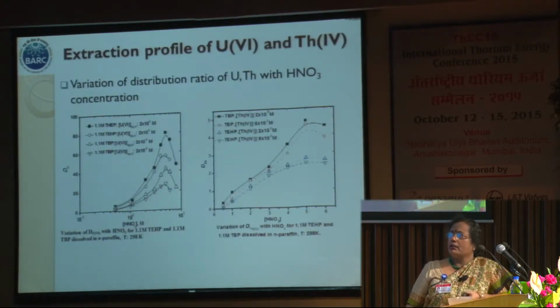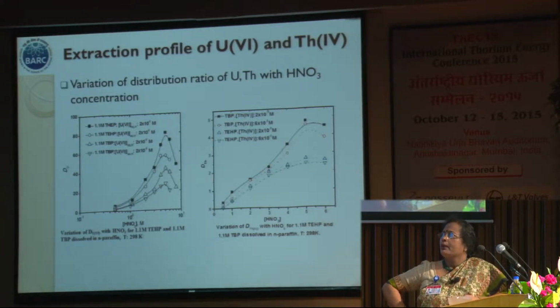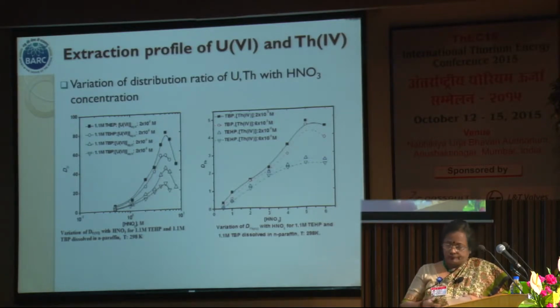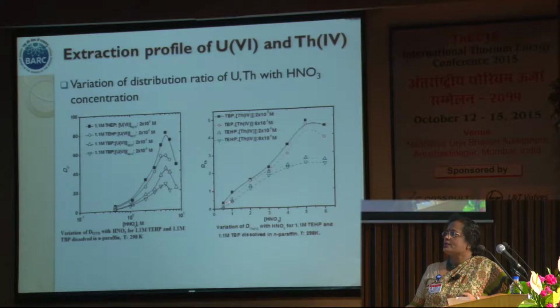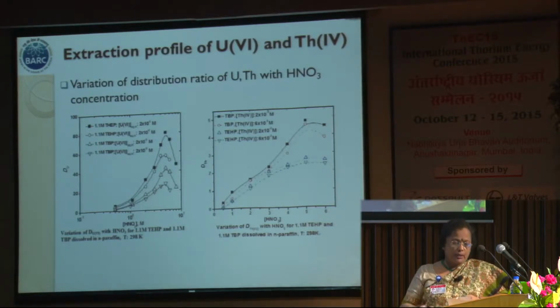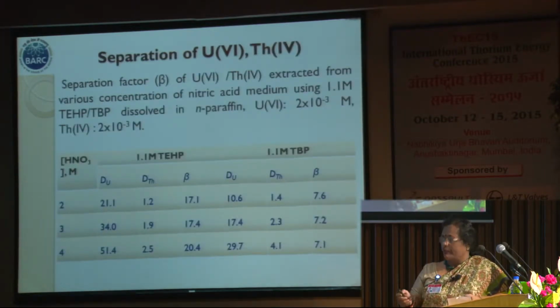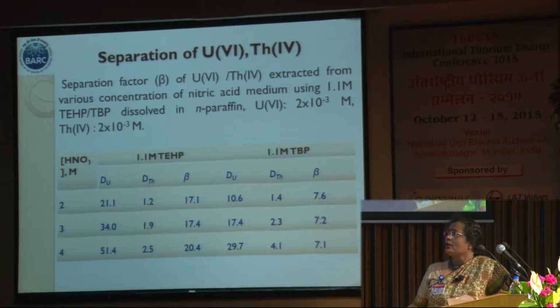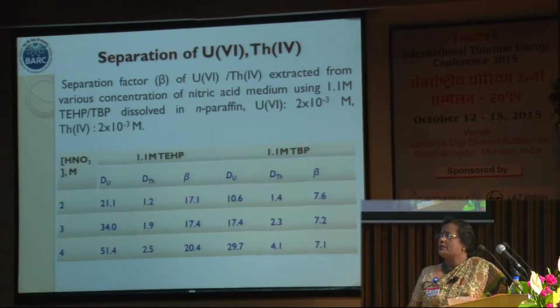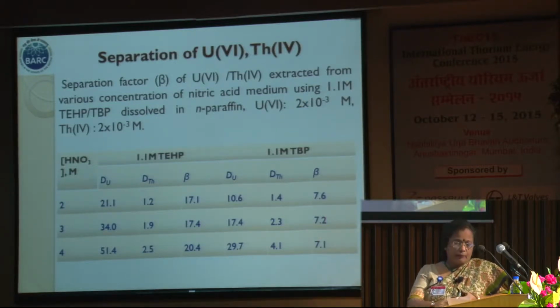Now in this we can see the distribution of uranium in this solvent is much higher than tributyl phosphate. This is for the TBP and this is for our THP. And in case of thorium, it is just the opposite. This is for THP and this is for TBP. So thereby we have a very good separation factor. We can see for 1.1 molar THP it is 17.1, whereas in the case of TBP it is 7.6, and it has gone up to 20.4, whereas this remains near about 7.